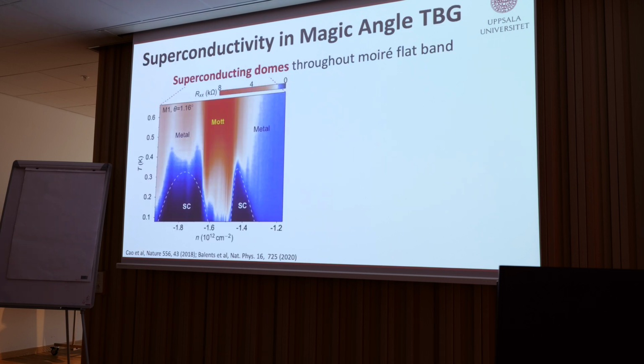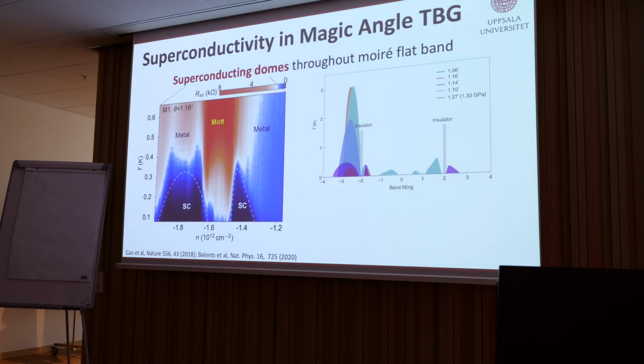We already saw this picture from earlier this morning: there are superconducting domes found at the magic angle in twisted bilayer graphene. There are several domes, interspersed with what seems to be some sort of correlated insulating phase. And there have also been results seeming to find, at least in twisted bilayer graphene, superconductivity in a range of fillings.